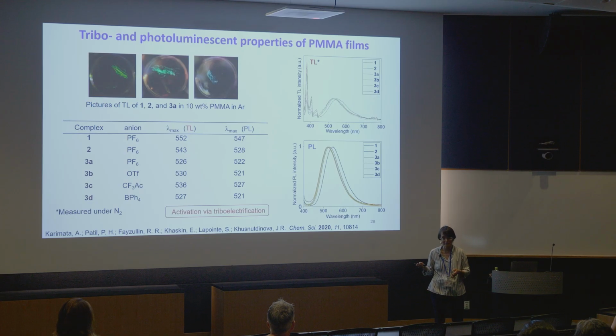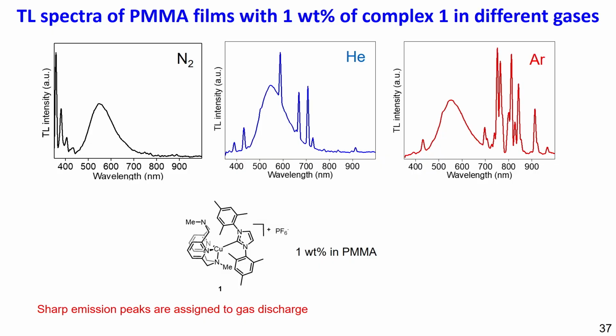And this gave us some idea about the possible mechanism of why we see this triboluminescence in the polymer films, which are amorphous. Most likely it involves the triboelectrification of the polymer matrix when you rub two dissimilar plastics against each other. So more like a static electricity build up when you rub the wool against the balloon or the styrofoam. So in all of the cases, we see that we have certain gas dependence in our triboluminescence in the film.